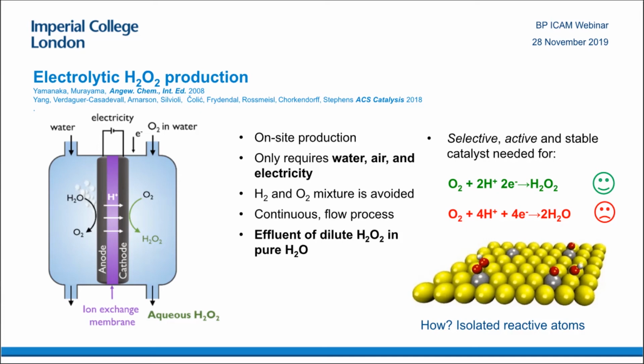But what was interesting about them is they always have isolated, very reactive atoms surrounded by more inert substrates. So in the case of palladium gold, they have an isolated palladium surrounded by gold. So we had the idea, let's look for an alternative to palladium gold. The problem is that the catalysts people have already reported are not very active.